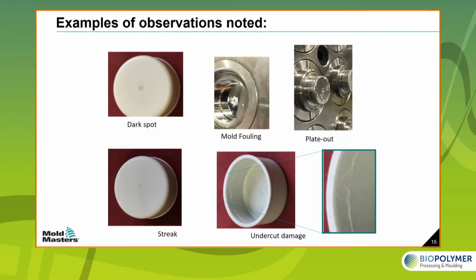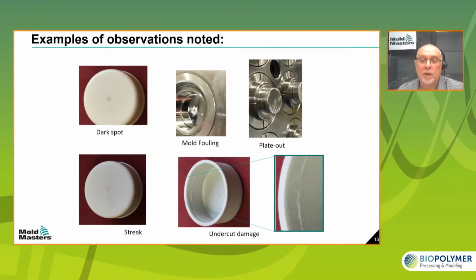And here are some examples of several different materials that we're molding, and some of the results and observations made. So on the first one, we see that we were getting a dark spot in the gate area. That may or may not be objectionable, but it's noted as occurring with a certain material. Mold fouling, we can see there's some pickup happening around the gate area, and that may cause a cosmetic defect. And if that's objectionable, then the mold may need to be stopped at regular intervals, maybe a half hour, maybe an hour, depending on the quality demanded and the appearance that is happening. But it's good to know that that is a potential issue with that specific material.